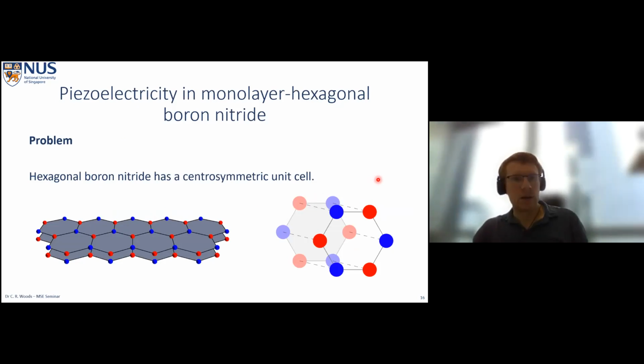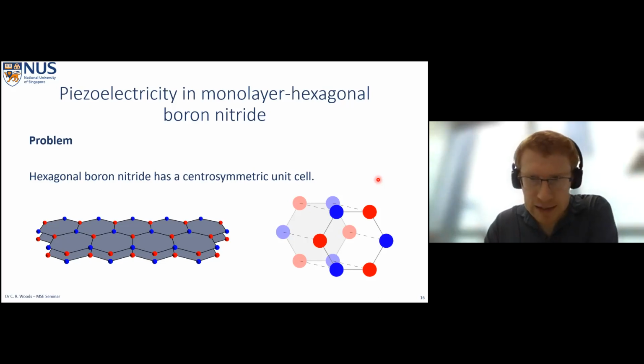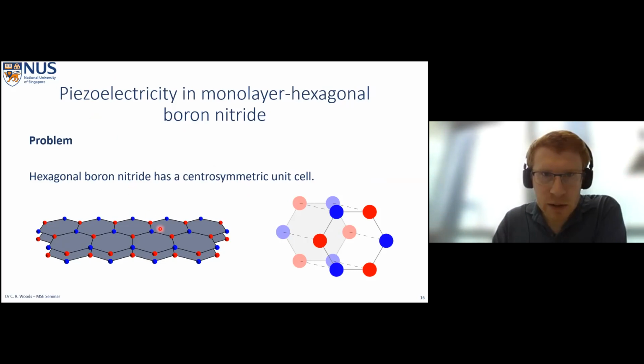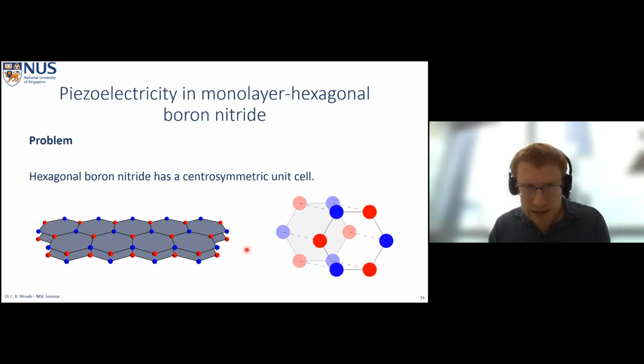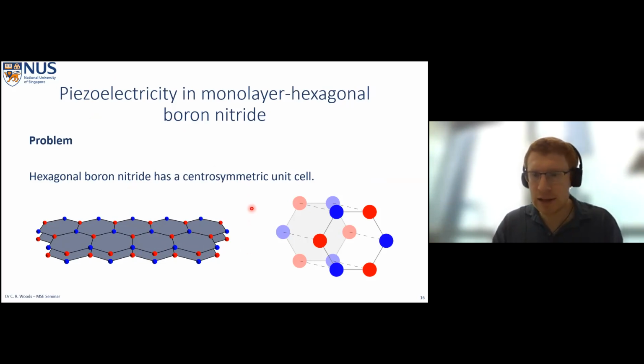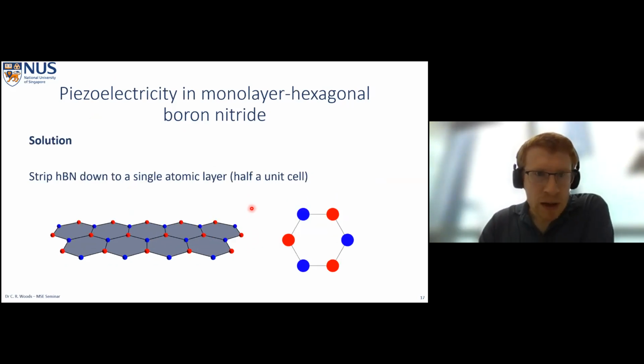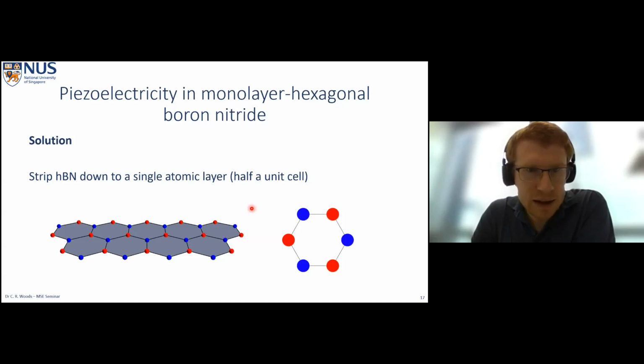Right, so let's meet our first problem, which is that hexagonal boron nitride has a centrosymmetric unit cell. And that is to say that if we invert it, we get something which looks the same. In terms of piezoelectricity, specifically, that means that if I strain it, if I get a polarization in one of our layers, then because the adjacent layer is the inversion of our first layer, we'll get the same polarization in that layer, but it will be pointing in the opposite direction. So the polarization fields will exactly cancel each other out, which is why we won't see any piezoelectricity for hexagonal boron nitride. And of course, the solution, if you read the title, is to just strip the hexagonal boron nitride down to a single atomic layer.